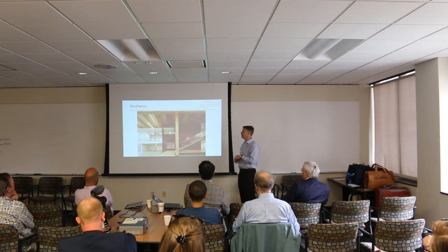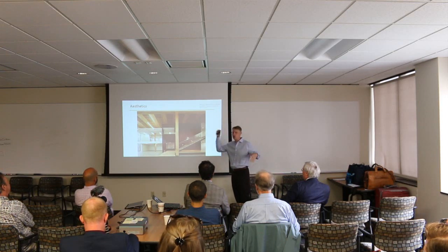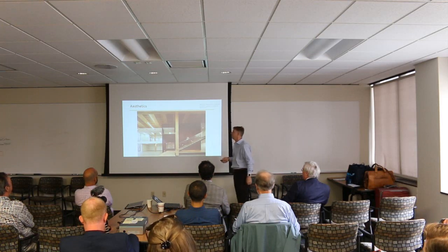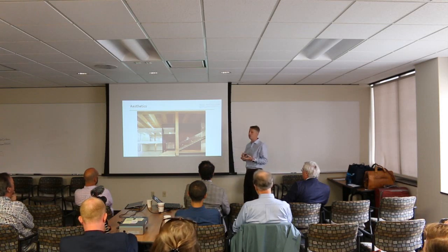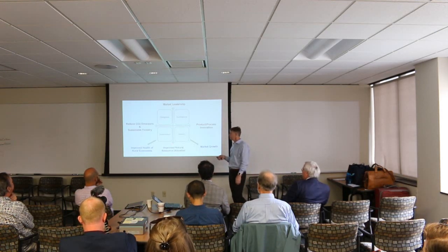So with D.R. Johnson on the tall wood project, we actually did a separate fire test with it exposed, which is typically what the designers want. And with that, we have to be careful. It does create smoke, and that's the biggest concern. When firefighters go into the building, is there too much smoke, and can they find their way through to get occupants out of the building? That's the big concern. It's typically not charring and structural failure, it's how much smoke development. There are finishes we can put on the wood to reduce flame spread and smoke development, but it's something to be aware of.